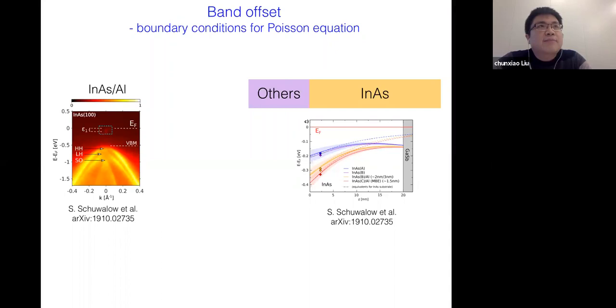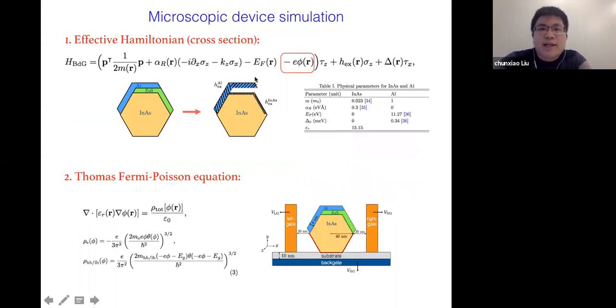But the magnetic proximity effect between aluminum and europium sulfide is not treated rigorously. We only add an exchange coupling inside aluminum. For the superconductor, we didn't solve the self-consistent gap equation. We just use the simple s-wave superconductor model without self-consistently solving the gap, but we self-consistently solve the electrostatic potential in the indium arsenide.